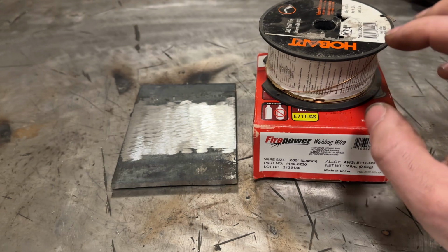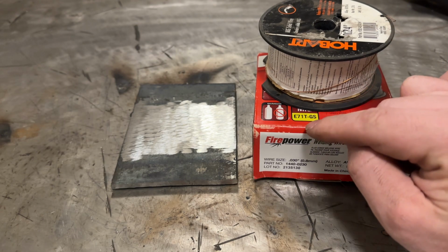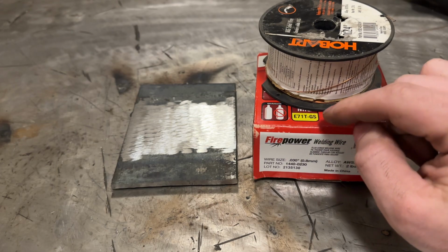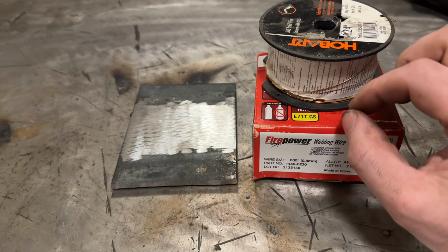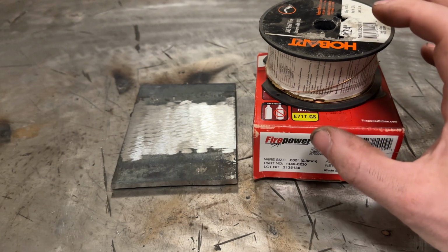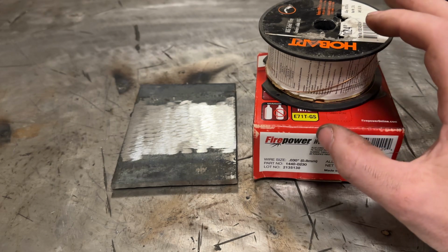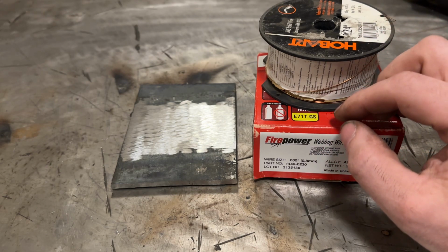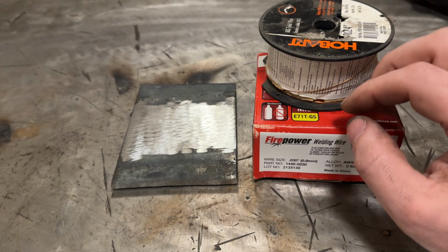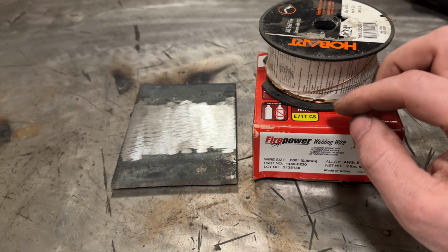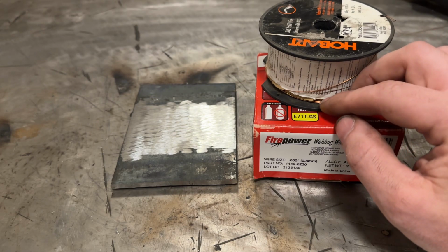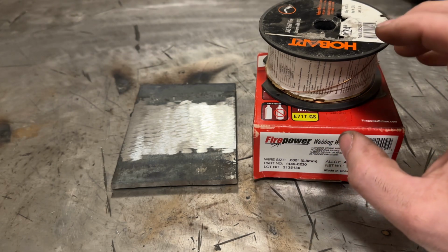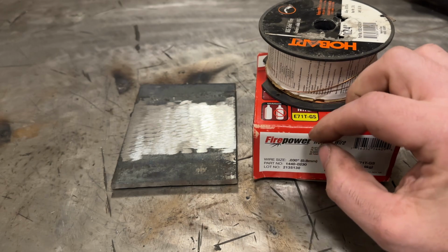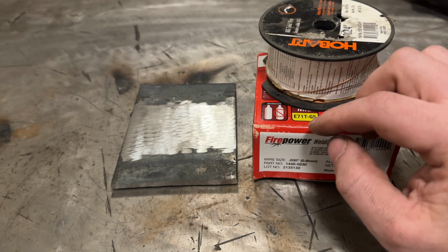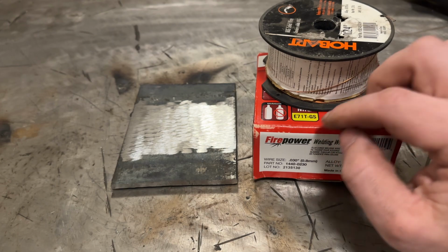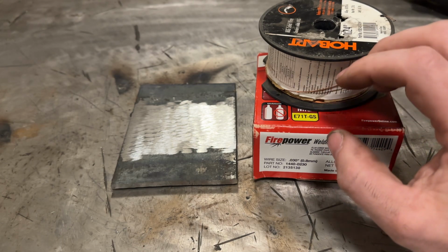And I want to mention that using shielding gas with a process like self-shielded wire, I have a feeling is going to create differing results. And what I mean by that is CO2 itself arguably qualifies as an active gas. Like the higher the percentage of CO2, it has an effect on the arc. It actually increases the voltage in the arc gap and increases heat input. Well, using something with a decent amount of CO2 on a process like self-shielded wire, I have a feeling may actually increase the heat input into the weld, which may not be desirable. So that's problem number one.